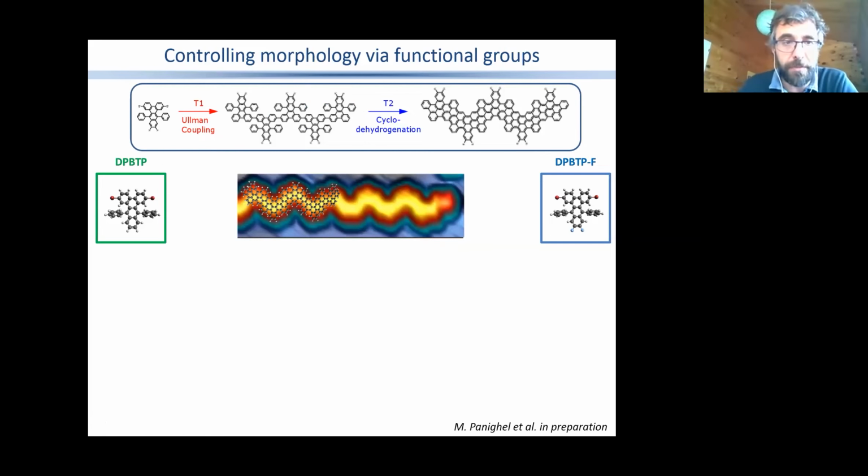These molecules, these precursors, again, we have bromine atoms here. So these are the ones involved in the first reaction, but all this structure is planar. That means that this planar structure will like to interact quite strongly with the surface because of the pi interactions of this aromatic backbone. And the interactions will be quite strong. And again, it will be preferred to be interacting with the FCC domain than the HCP.